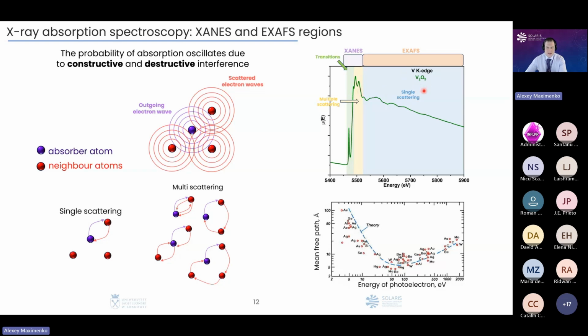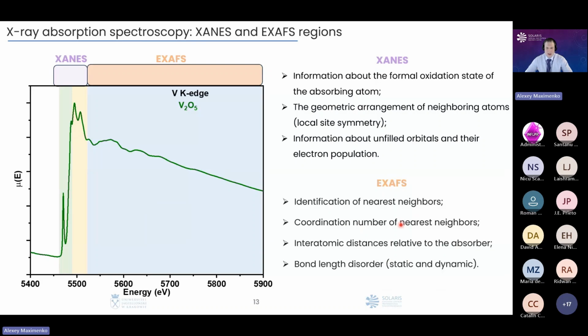In the case of the EXAFS region, the energy of this photoelectron is large, and that is why its mean free path is low. It means that mostly for the features in the EXAFS region, we have influence from single scattering paths. That is why it is easier for EXAFS to investigate parameters such as interatomic distances and coordination number, in comparison to XANES, where we could get information about geometric arrangement, or symmetry. Now we understand the basics.